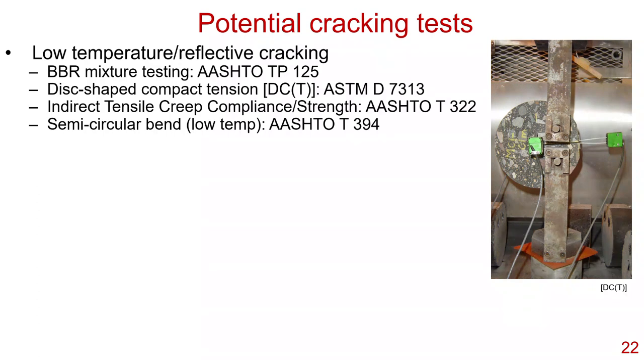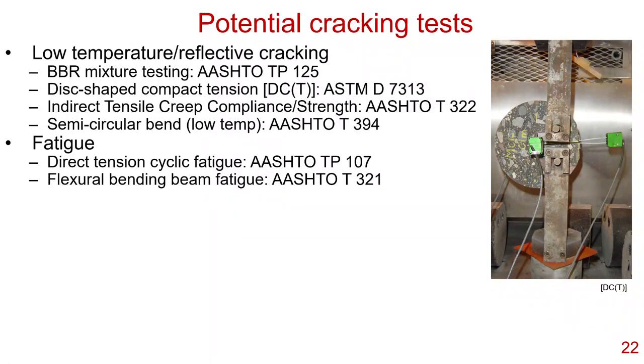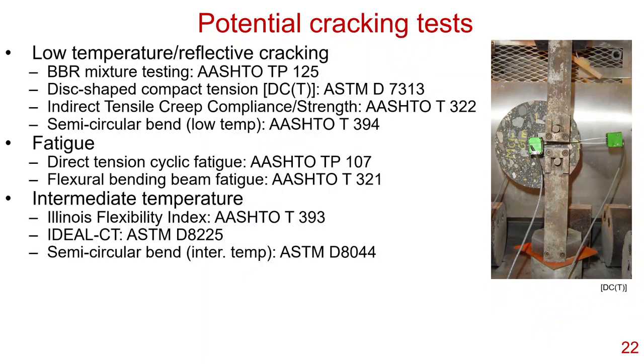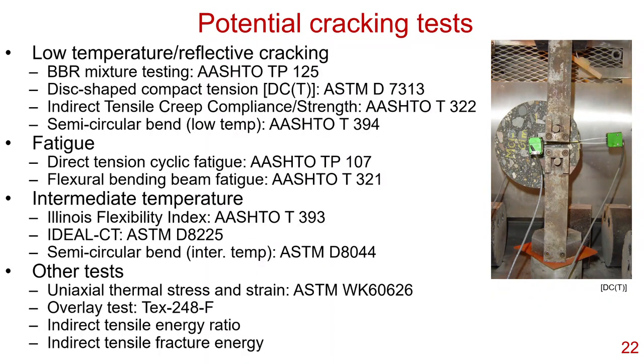You can also look at the indirect tensile creep compliance and indirect tensile strength, the semicircular bend at low temperatures. That's very important. You can look at fatigue. This includes the direct tension cyclic fatigue and the flexural bending beam fatigue. You can also look at intermediate temperature cracking, the Illinois Flexibility Index, the IDEAL-CT, and then the semicircular bend at intermediate temperatures. And then finally, there's various other tests that can potentially capture cracking, the uniaxial thermal stress and strain, the overlay test, and then the indirect tensile energy ratio and fracture energy. And you can see all the associated standards with that as well. A lot of numbers, a lot of letters, but a lot of good information there.